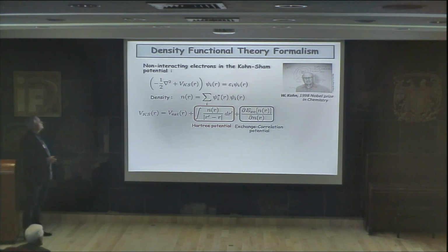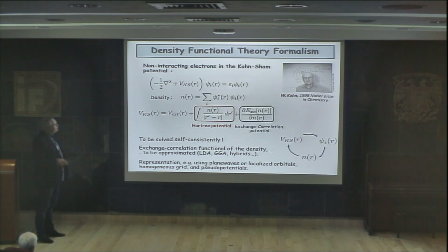So in fact, in this talk, I will mainly focus on the density functional theory formalism, which is a theory for non-interacting electrons, which are in a Kohn-Sham potential. So you have the Kohn-Sham potential that is here, and this Kohn-Sham potential contains the external potential for the electron, the Hartree term, and also an exchange correlation term, which takes into account several quantum interactions. And the way we work, in fact, is that we use a trial density, which is really the most important variable in this theory, and we construct the Kohn-Sham potential, and from this Kohn-Sham potential we solve the Schrödinger equation to get the wave function for the particles, and then we can reconstruct, in fact, the electronic density.